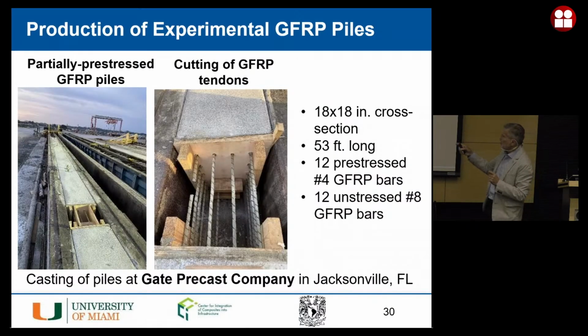So this is an exciting thing. This is the project of casting piles with GFRP tendons. So these are number 4 rebars, so 12.5 millimeter in diameter, that we could have in a coil, so we could run them for the entire length of the bed, that is in feet 450. And so we could cast these piles, and we only pull the tendons to 40% of their ultimate because of this phenomenon of creep rupture.